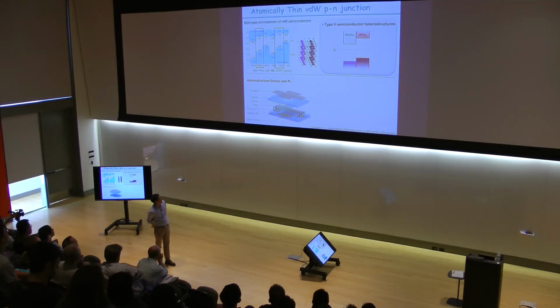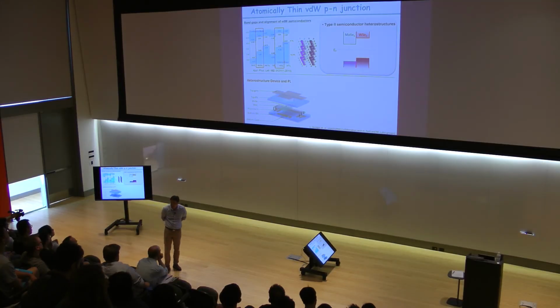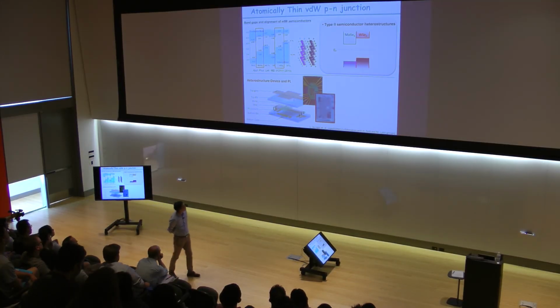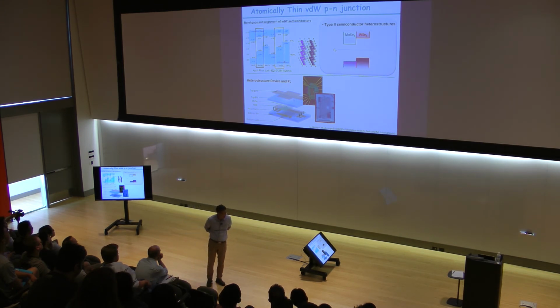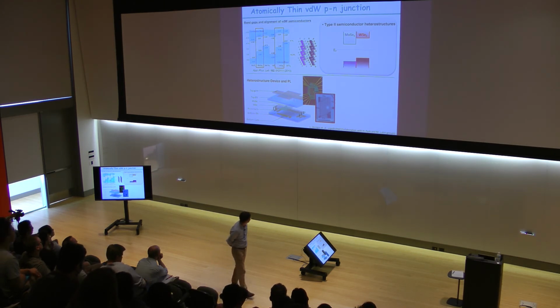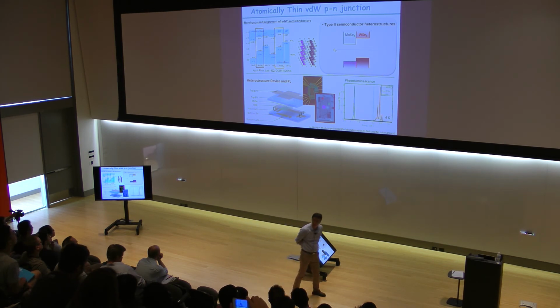We can create the photoluminescence, and we can get the electroluminescence and photocurrents out of it. We can actually put a little bit more effort in here. We can put complete control, top and bottom gates, on each of the electrodes in each of the layers, and each of the electrodes needs to be gated to make the ohmic contact. But at the end of the day, we have the device. By the way, this is kind of a heroic effort by a couple of students, and making this type of device takes some time to build a working device. But nevertheless, once you make the device, you get a beautiful optical spectrum.